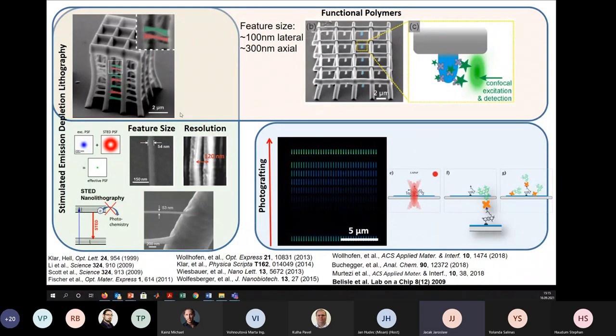And in the past, we worked a lot with functional polymers, especially during my time at the JKU. I was working with different types of resins, and we were able to combine them into one single structure. So we used polymers with different reactive groups on surfaces. For example, here is a structure consisting of 3 different types of polymers. The one is polyethylene glycol based polymer, which is protein anti-adsorptive.